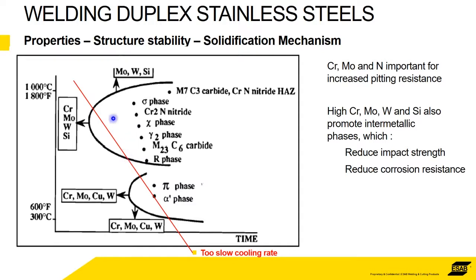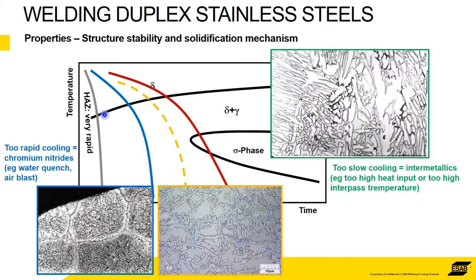The presence of these phases, the sigma phase, the chi phase, they're like little pockets of weakness within the microstructure. So you can have what looks on the surface to be a nice duplex microstructure. However, there will be intermetallics within there, and I've got an illustration of that on this slide. This has taken too long to cool, and you've got these dots of intermetallics, little pockets of weakness. These are areas within the structure that are weaker than the surrounding areas. They don't have the mechanical strength. They don't have the corrosion resistance. So too many of those, and the structure is no good.